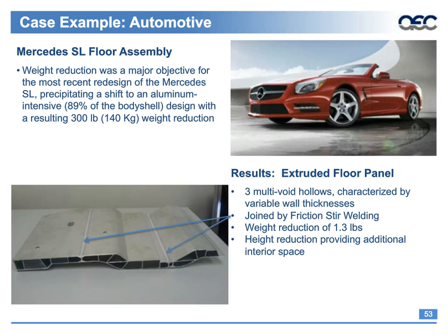That profile, there's three different extrusions that make that up with varying wall thicknesses. The three pieces are joined together by friction stir welding. So overall, the assembly is 26 inches. A 26-inch extrusion die would be very expensive and difficult to run. You wouldn't be able to run it with these thin walls in here. So it got redesigned into three different extrusions, welded together, and they have a much lighter floorboard. And the height of it is lower too than what the steel was before, which increases the inside room.